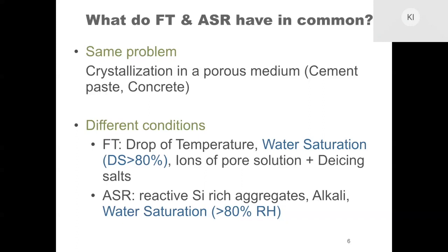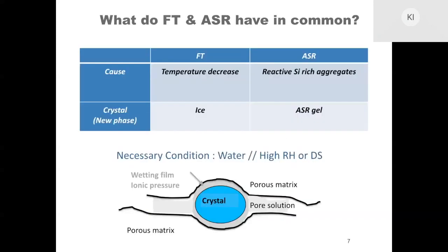In the case of alkali-silica reaction, the reason why we have this damage is the silica-rich aggregates that start reacting after many years inside the concrete. So basically, the presence of alkali is the reason, but also in this case, the material needs to be saturated in water, otherwise the damage is not propagating so fast. As you notice, we have here two different reasons why we get this damage. And in each case, we get a different phase. So in the freeze-thaw, we have ice.